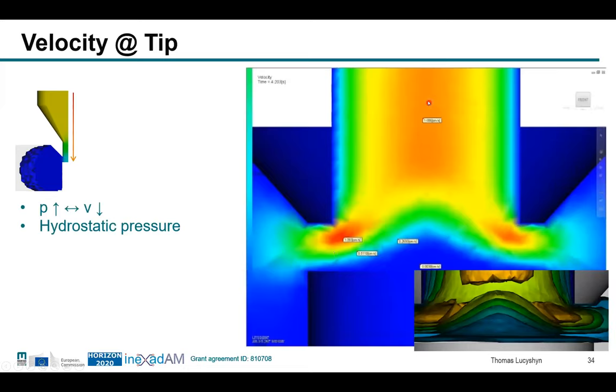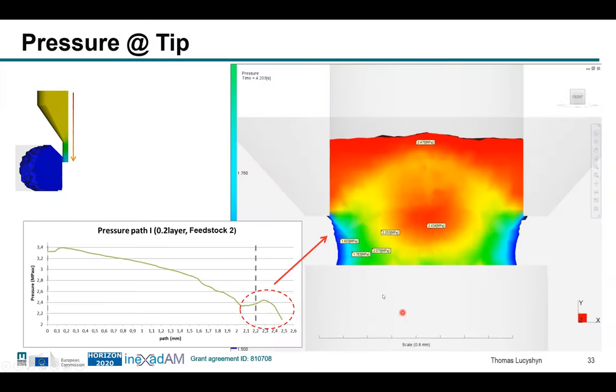You can see it here. Here's the velocity. So most of the material goes out here, but here it's kind of stagnating and then producing or pushing the material against the wall, creating some additional pressure here, which we saw in this peak. So that was at least some explanation why we had this peak, which was not usual.